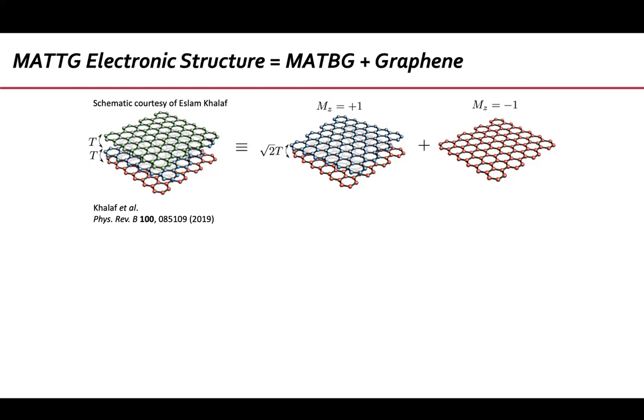The square root of two T here means that the magic angle for magic angle twisted trilayer graphene, as I mentioned yesterday and reminded you earlier, depends on that interlayer tunneling. Because of this square root of two T, the magic angle for twisted trilayer graphene is that of bilayer times square root of two, okay? So it's 1.1 times square root of two, which is 1.56 degrees, okay? That means that the Moiré wavelength is a little bit shorter because a larger angle means a smaller Moiré pattern, which means electrons are a bit closer and will interact a bit more strongly, okay?